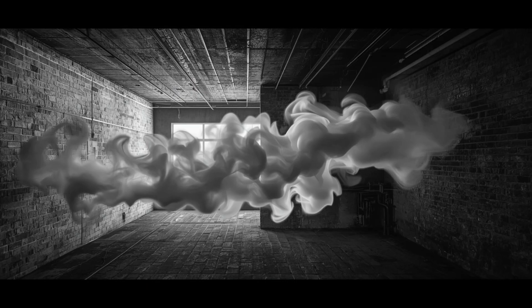Boundary layer separation along the refractory walls added another reinforcing mechanism. On the cooler left side, carbon from incomplete combustion deposited on the brick, creating a rough, insulating layer that slowed flow near the wall and reduced heat transfer to the structure. On the hotter right side, complete oxidation kept the brick clean, maintaining high heat transfer and allowing gases to flow faster along the wall.